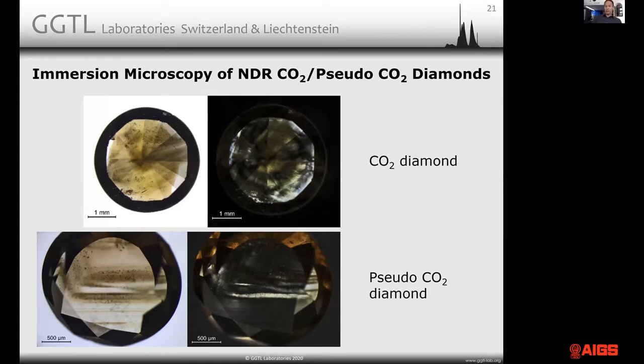Then on the bottom you see what we call pseudo CO2 diamonds. These diamonds often, instead of a color patch, have some sort of color zoning. They're parallel and do not relate to extinction patterns from deformation, but they show a couple of bands that actually show strong extinction. You can see on the left side, in that diamond in the middle, there is one plane that's kind of olive gray in color. That olive gray plane is the one that extinguishes completely, gets dark. Upon rotation, every 45 degrees, it will go light, dark, light, dark. So these are the only bands that do this in these diamonds. Very unusual diamonds.